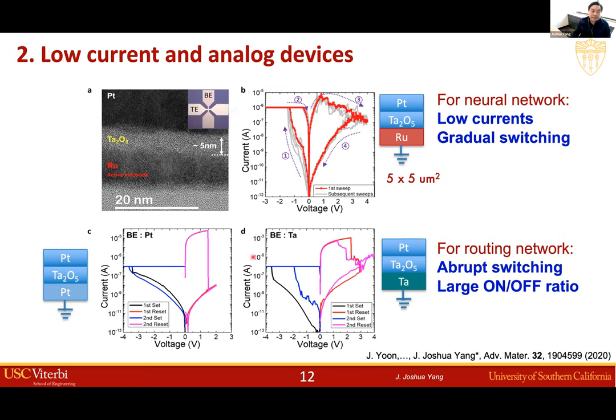it's quite different from the memory application in that you are operating all the devices in the larger array in parallel simultaneously. So each device needs to have a low current and high resistance so that the total current would not saturate your periphery circuit and the total energy consumption can be low. But traditionally, the device has abrupt switching behavior, relatively high current. This can be used as a routing network in FPAA, but is not very suitable for neural network in the FPAA. For neural network, we need to develop a new type of device to achieve low current and gradual switching.